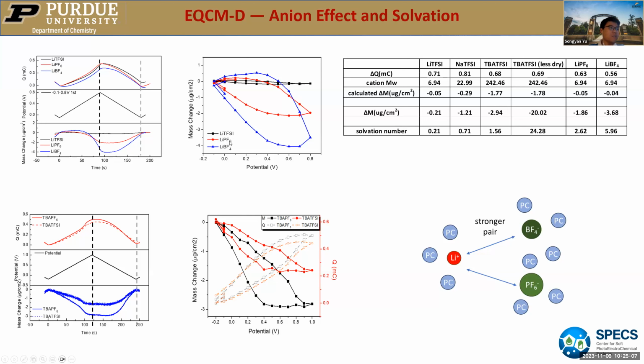But the difference between lithium PF6 and lithium BF4 is kind of interesting. If we assume they both do not participate in the doping and de-doping process, then the difference may come from the solvation of these two electrolytes. Because lithium forms a strong ion pair with BF4, surrounded by PC solvent, in order to break this ion pair we need a larger solvation shell. So that may be the reason BF4 had a larger mass transport than lithium PF6.